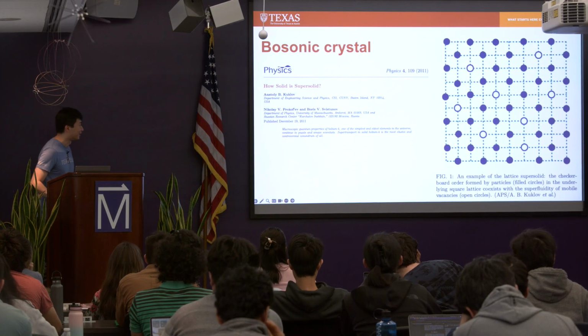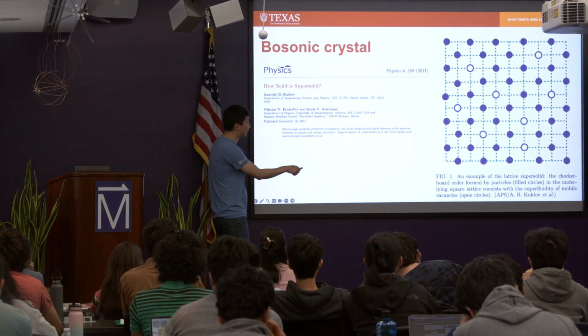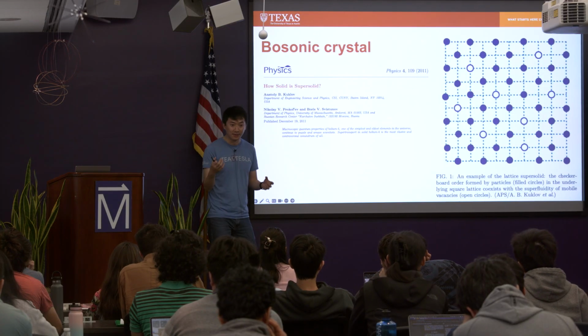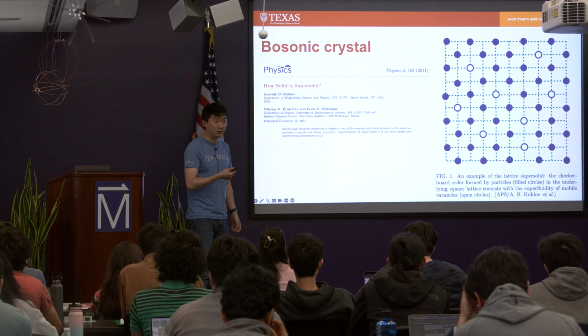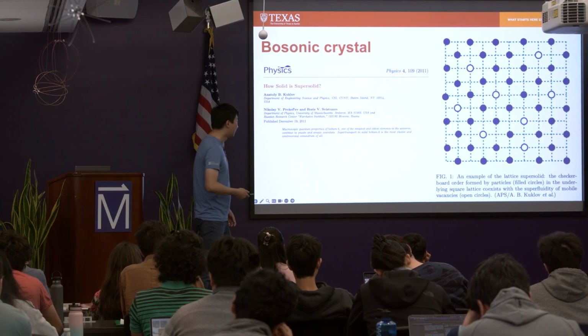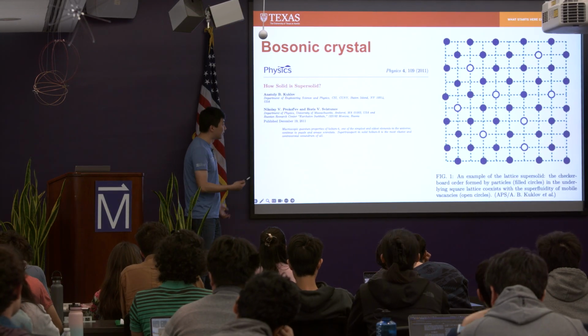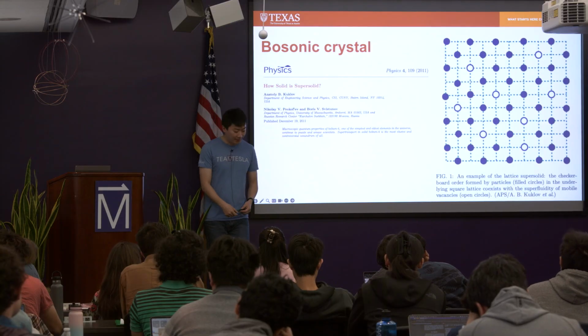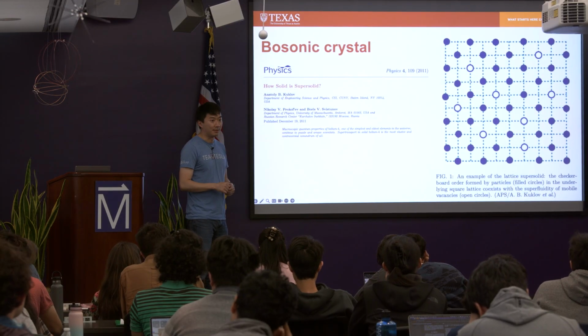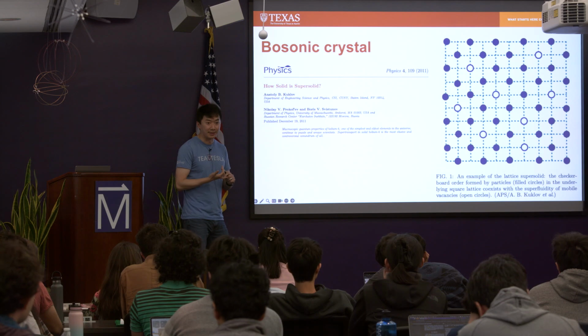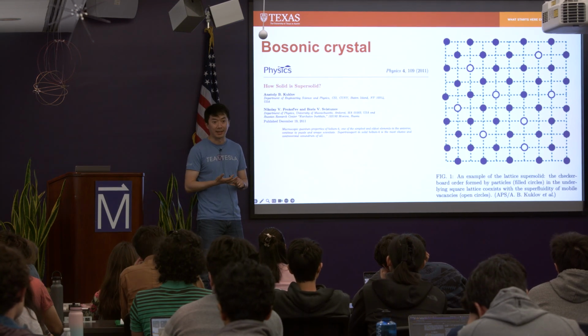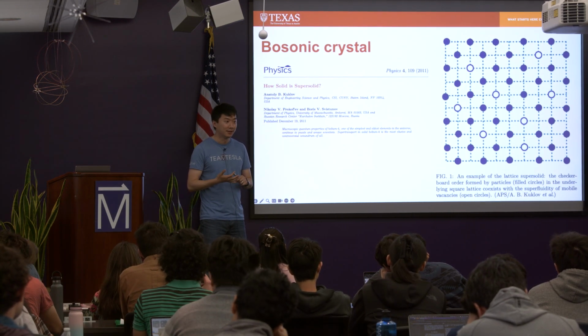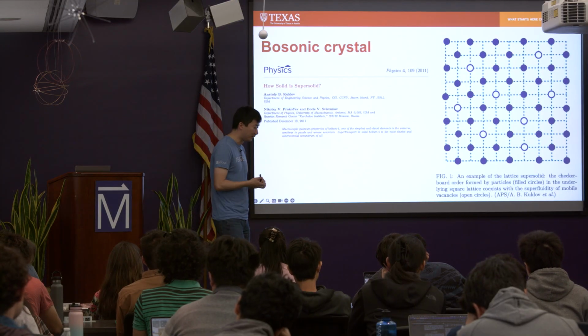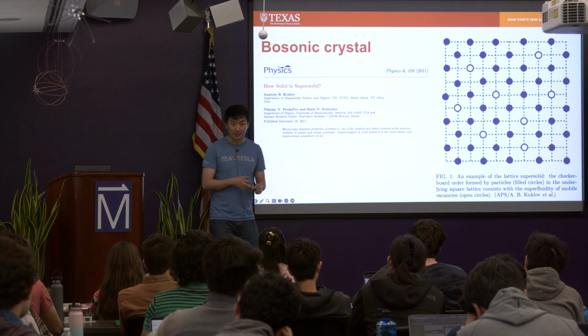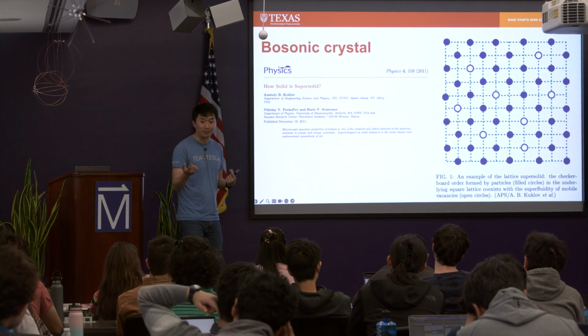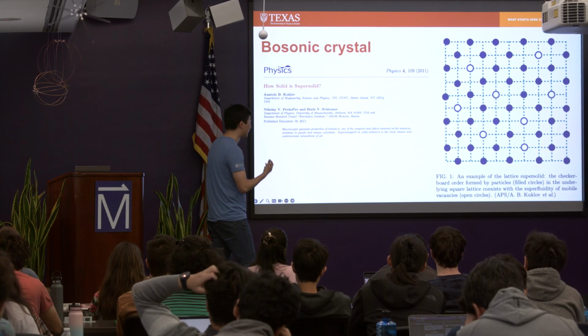My understanding is that the supersolidity really happens for the vacancy in the crystal, right? When you have this supersolid, the vacancy is free to jump around without dissipation. Right. So this is a very intriguing quantum state of matter, and the main challenge for us to realize it experimentally is that we just don't have so many bosonic states in solid state materials, right? You need a bosonic state, and you need to get to the right condition for that to form a solid, and you probably want to be able to do transport measurement on it, right? So that you can detect this supersolidity.